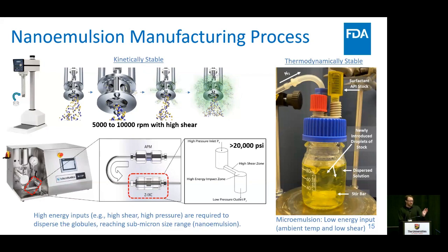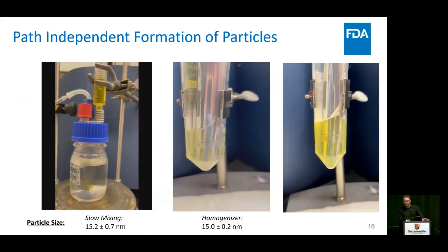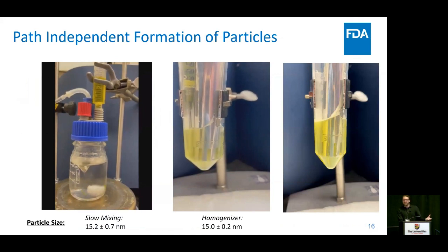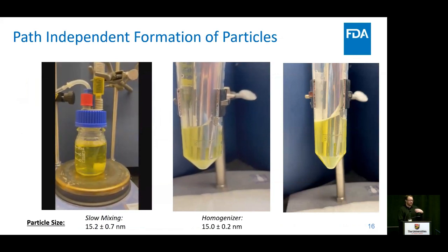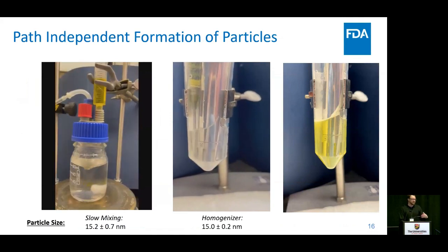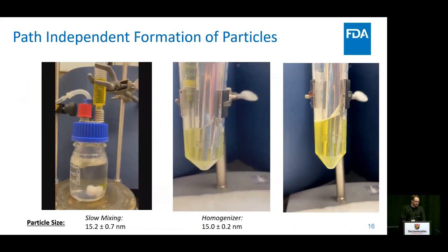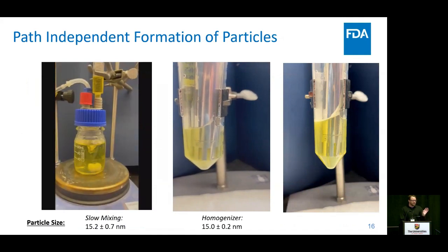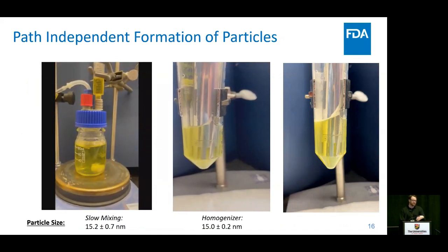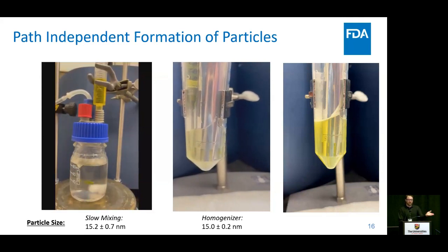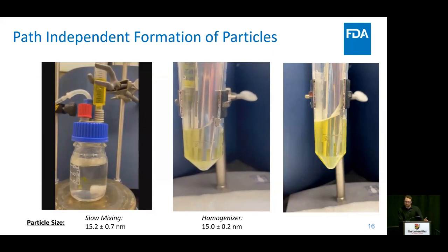And so in general, for a thermodynamically stable system, it should be path independent. So as opposed to the kinetics where your manufacturing process will strongly impact it, if you're looking at these thermodynamically stable systems, you can basically either use a homogenizer or a very slow mixing technique and get the same thing that might take 30 minutes in about 15 seconds.